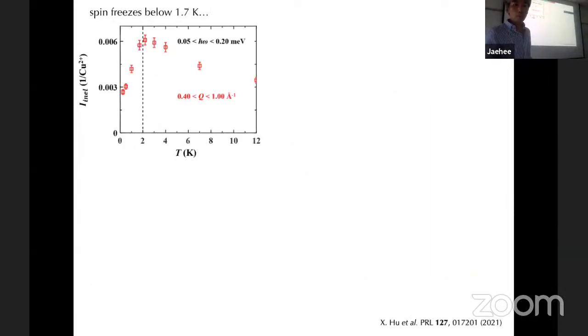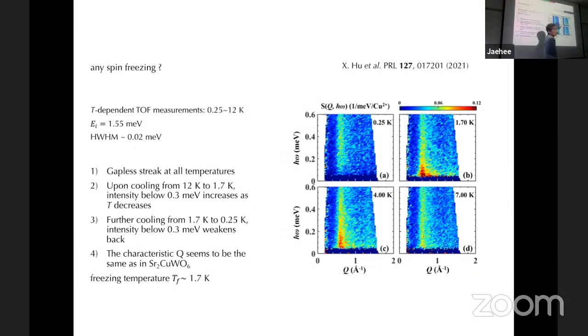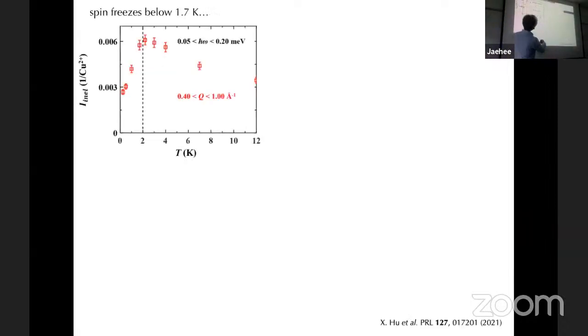So, immediately when I see this kind of data, there must be spin freezing, because spectral weight, in fact, goes into the elastic channel. That's why you get depleted. And then we integrate. We did this kind of measurement at many temperatures spanning TF, and then we integrate this spectral weight around here and plot it as a function of temperature. Then you can see here from 12 Kelvin it goes up, and then around 2 Kelvin it goes down. So these are inelastic. This spectral weight decreased and goes into the elastic channel. So there's a spin freezing.